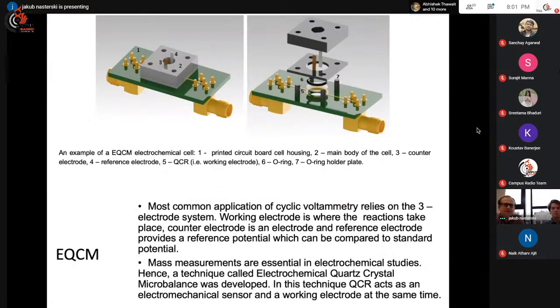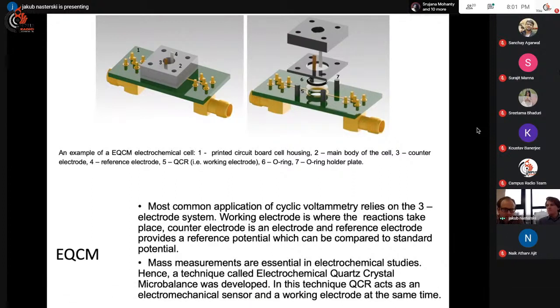So then people combine both of these techniques, so electrochemistry and QCR methods, and the result was what is called EQCM, so electrochemical quartz crystal microbalance. Essentially, when people do cyclic voltammetry, they usually use 3 electrode system, where working electrode is where all the reactions take place. Counter electrode is an inert electrode, and reference electrode provides a reference potential, which is then compared to standard potentials of other systems. So that essentially, reference electrodes provides you with 0 point.